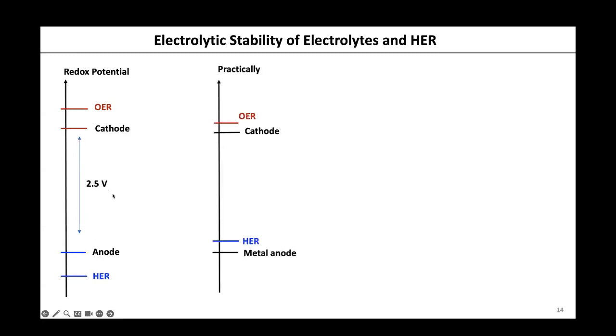2.5, hopefully. Now the reality is our metal anode is operating below the hydrogen evolution potential, so water can be reduced by the zinc metal, right? And often the operation of the cathode is frustrated by the oxygen evolution. That is because they are close enough. Now, two solutions. One is to move this HER down there, right? So we need to tune the thermodynamic stability window of the electrolyte. And then the second solution is to grow a solid electrolyte interface to passivate the surface of the metal anodes. And today I'm going to introduce these two solutions to you.